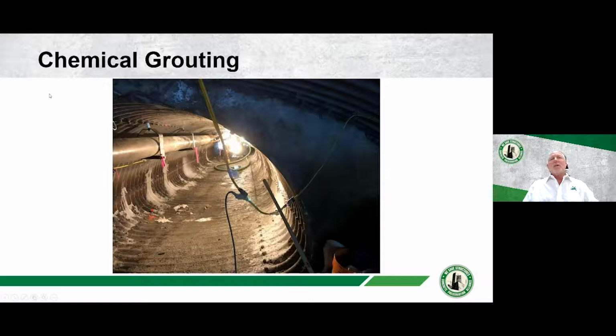Once we got in here, we found that there was a lot of leakage from groundwater going into the pipe. So actually a chemical grouting was done ahead of time. Went in, drilled holes through the culvert, pumped a urethane chemical grout in behind to stop the water. And you can see how dry we were able to get the pipe before we sprayed it. You can see the diversion pipe here hung up in place, so out of the way.